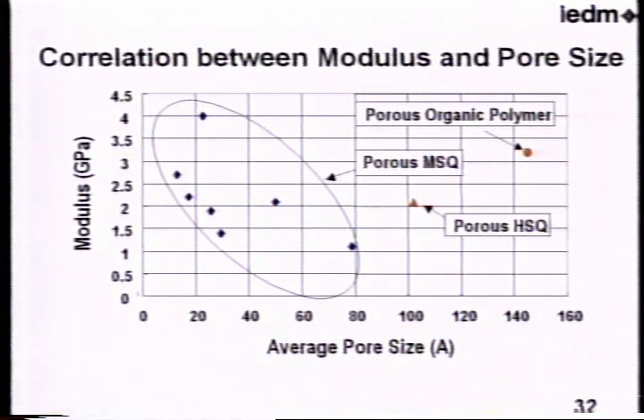And also, there is some correlation between the modulus and pore size. The pore size was evaluated by using a small angle X-ray scattering method. This is a figure of the correlation between the modulus and average pore size. There are big scatters among these materials, MSQ, HSQ, organic polymer. However, there is some strong correlation if the material is restricted to MSQ, porous MSQ, like this. So, small pore size and tight distribution makes the porous MSQ stronger. So that's very important to control this kind of pore size or distribution in developing Low-K materials.